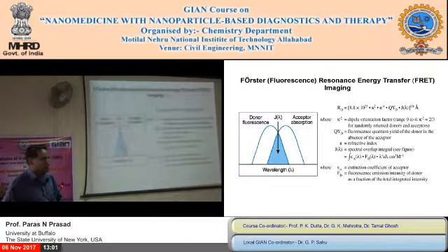Okay, so this is why nano formulation is very important if you want to use FRET for sensing or others, because if you make 10 nanometer nanoparticles and you put these two dyes in there, or proteins, whatever, they are forced to interact. They are within nanoscopic distance automatically. The second thing, a requirement, is the distance dependence, which depends on the dipole strength and other factors. I don't want to go into details.